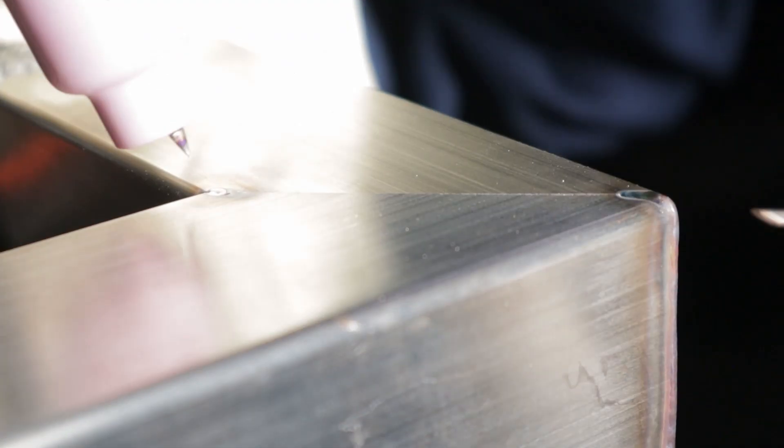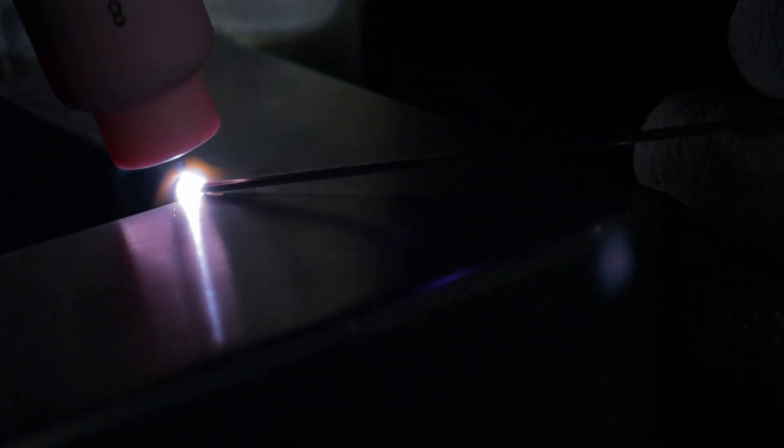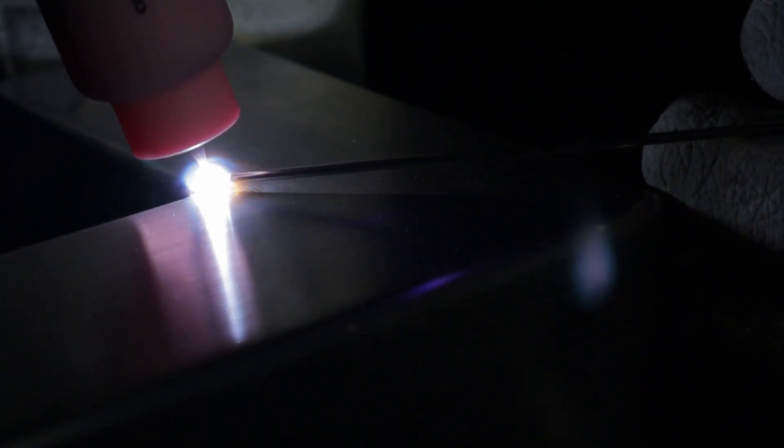And the face of this mitre is what you're after. Zero misalignment between the two tubes and zero gaps. I am using 1/16th wire or 1.6 mm on the seam and I use just over 3 inches or 80 millimeters.